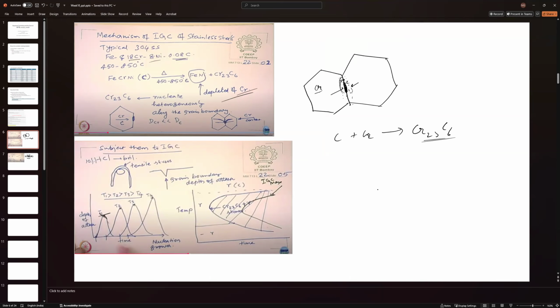So at low temperature, you have limited diffusion of chromium toward the grain boundary, and you don't get that much depletion of chromium near the grain boundary. As you increase the temperature, the diffusion would increase, and this region would get more easily depleted. At a certain temperature, you will get the maximum depth of attack, right? If you go even further to higher temperature, the nucleation of this precipitate becomes thermodynamically unstable, and you don't form these precipitates. And since you don't form precipitates, the chromium doesn't get consumed and stays in the grain.